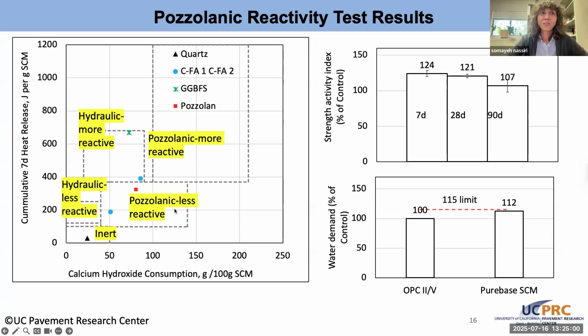We've tested so many materials at this point that we've come up with boundaries and boxes for how to label the material. We've also checked that with some of the work available in the literature, and the boxes kind of match up. So you can see that the Purebase material that we're using as an example today falls in this middle area, which we like the material to fall in, pozzolanic. What we call less reactive is here versus this area where we get a lot of heat, and those are the super uber reactive materials. We're not necessarily looking for overachievers. We're looking generally for materials to be in this area. And then some of the other materials may be latent hydraulic, which fall in these other boxes.